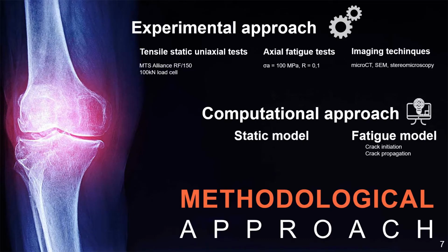In order to isolate the effect of lacunar morphology on damage progression, healthy bone lacunae are replicated in samples made of titanium alloy, more in-depth titanium 6 aluminum 4 vanadium, realized by means of laser powder bed fusion at CNR, Consiglio Nazionale delle Ricerche, Lecco, Italy. An additional notch is introduced to simulate external surface discontinuities, typical of natural bone samples.